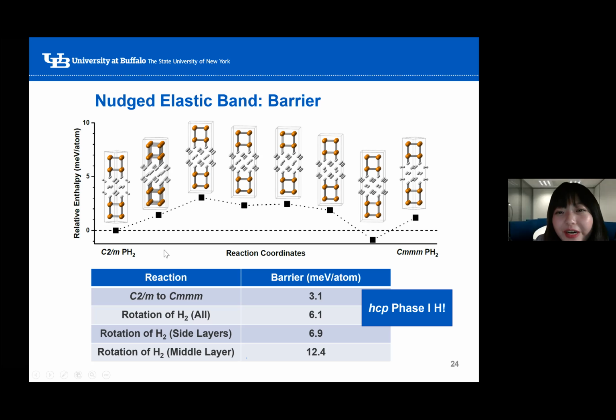Oh, so you mean this page, right? Right, yes. What we did is we started one connection by connecting the C2/m and the Cmmm phases, and the intermediates are just rotating, slightly tilting these H₂ molecules to get to each other. Then we calculate the barrier, which is the structure with the highest enthalpy. We did the same, but rotating different layers for C2/m. We did three runs. First is rotating all of them at the same time. Then rotating only the top and bottom layers. And another run is rotating the middle layers, just to see how this would affect the calculated barrier. I see. Yeah, okay, that makes sense. Thank you.